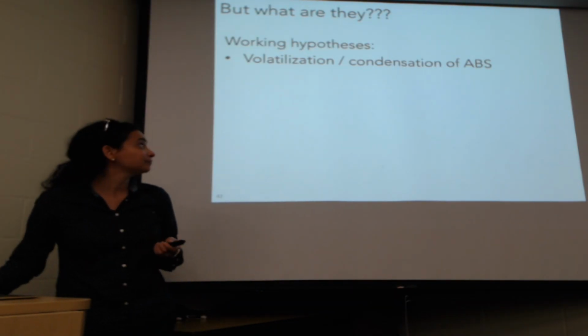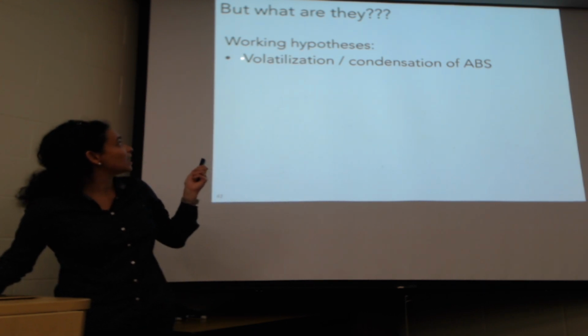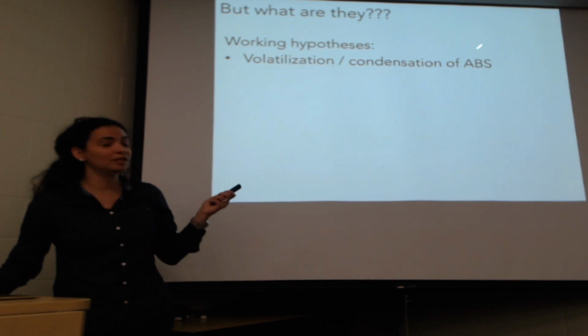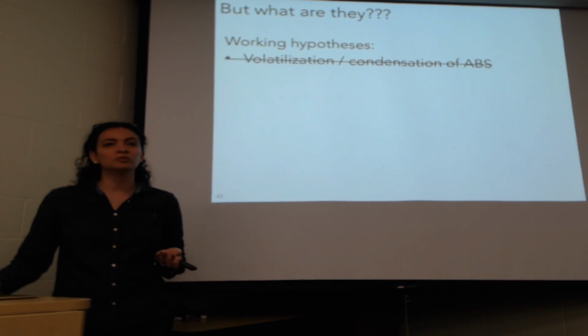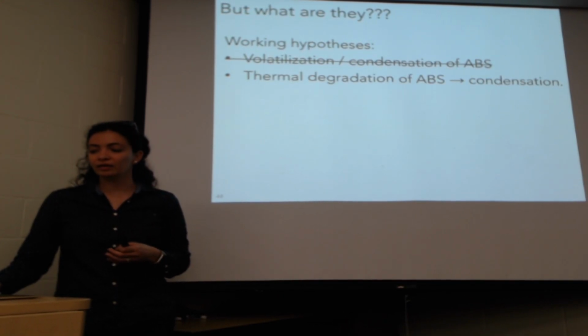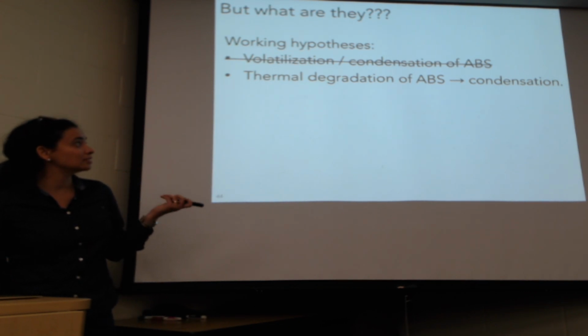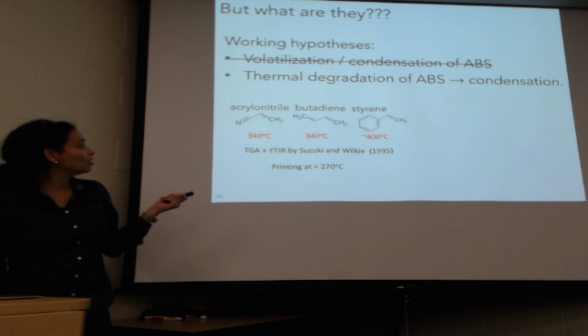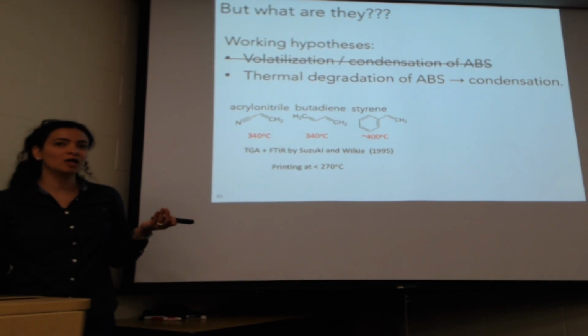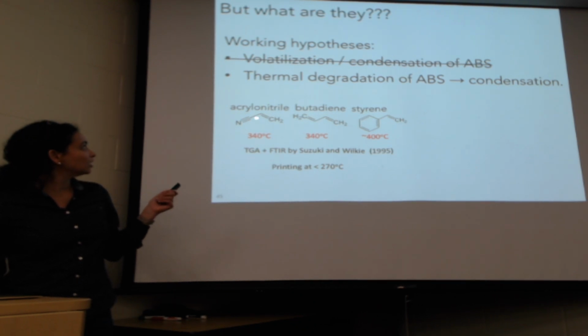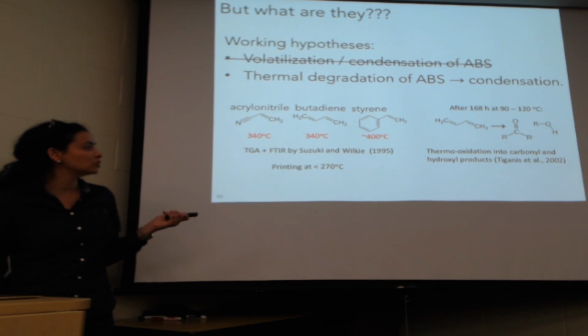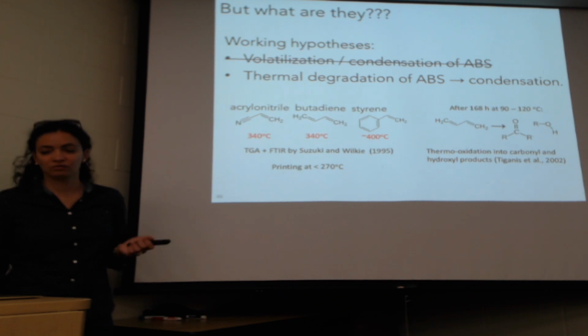So we have a lot of theories, a lot of working hypotheses. The first thing I mentioned to you was that chemical vapor deposition theory, that maybe the ABS is just evaporating and then recondensing. And I think we were able to disprove that by showing that those peaks just weren't there. Another possibility is the thermal degradation of the ABS, which is then recondensing onto particles. For that, we know there's some data showing that the polymer itself can thermally degrade at lower temperatures, but these three monomers take much higher temperatures to degrade themselves. Printing, again, happens at around 250, 270 Celsius. There is work that showed that if you spent a very long time at lower temperatures, you could thermally degrade the butadiene or other compounds as well.